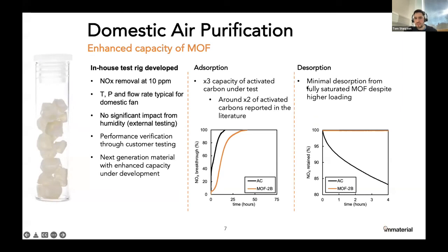And the last thing that we've done on these breakthrough tests was looking at the desorption. So now switching over the air flowing through from 10 ppm of NO2 to just a clean airflow. And here what we see is the activated carbon is now giving off quite a bit of NOx. And in contrast, the MOF-2B under these conditions is holding on to the NO2 tightly.